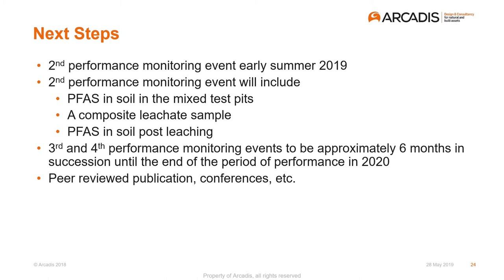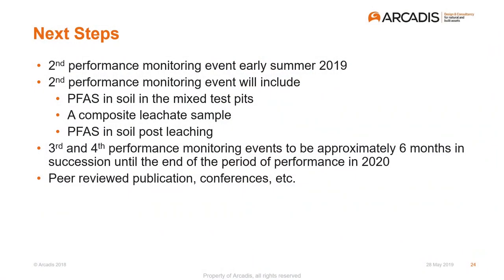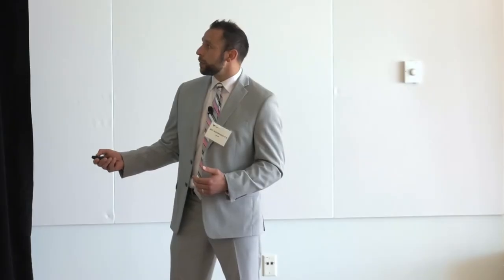And by that, I mean we're going to collect cores and analyze the PFAS in the soil of the mixed monoliths. So the FLUORO-SORB process, ISS, all this stuff, there is no destruction of the PFAS. They're just retained into a solid form that can't get into liquid. So we theoretically should be able to quantify that from a mass perspective. Then we're going to run a composite leach sample where we collect a subset of all nine leaches. And knowing the liquid that we've leached, we can come up with a mass that's leached off those cores. And then when we're done leaching, we'll run the PFAS in soil post-leach. So this should be the total mass, and the sum of these should equal that. So we're trying to close the mass balance to make sure that we're getting everything that we are leaching off.